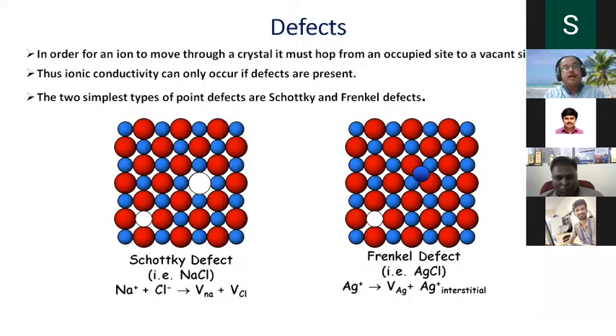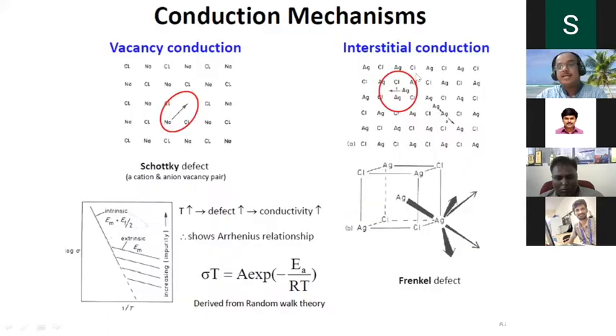The mobility is so good that you can improve the conductivity. So defects mean in order for an ion to move in a crystal, it must move from one occupied site to a vacant site. Thus, ionic conductivity can occur if defects are present. The two simplest types of point defects are the Schottky defect and Frenkel defects. You might have seen the Schottky defect, for example in sodium chloride, sodium plus and chlorine minus, and sodium ion vacancy. The Frenkel defects, you can see here. Similarly, vacancy conduction. So when you have a vacancy, then an ion starts to go from the occupied site to the vacant site. From here to here, jump. So a cation and anion vacancy pair is up here. So increase in defects helps to improve the conductivity.